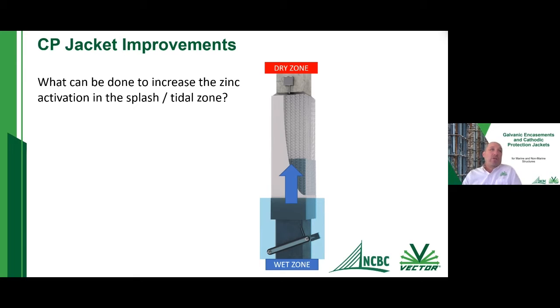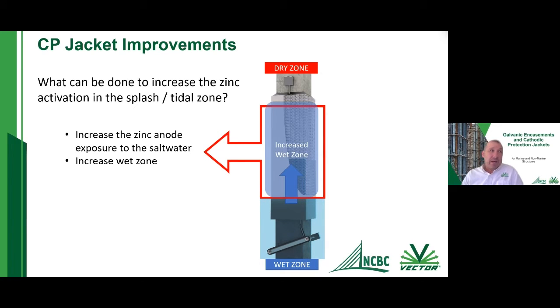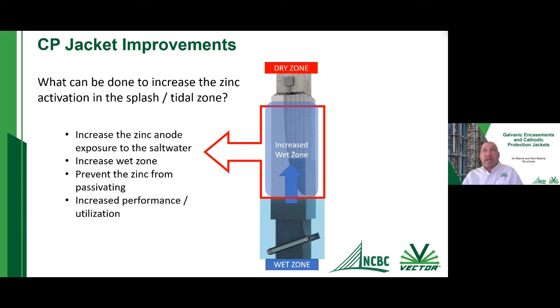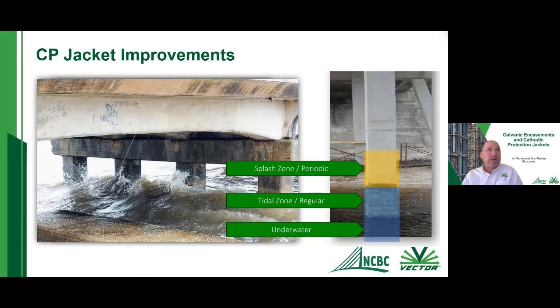So what can we do to increase this activation zone, or increase this tidal or splash zone? Because the zinc mesh is very effective in the smaller zone down at the water line, or in that tidal zone. But what can we do to activate the elevated portions of our jacket, to keep the zinc in a corroding state? Can we increase the exposure to salt water? Can we increase this wetting zone? If we can do that, we're going to stop the zinc from passivating. And by doing that, obviously, we're going to increase the performance of this jacket and elevate the area of our cathodic protection.